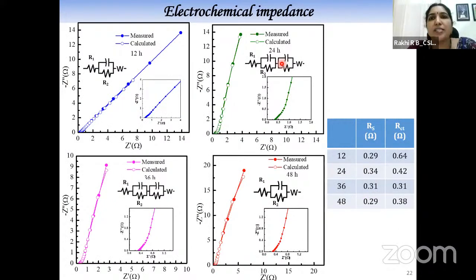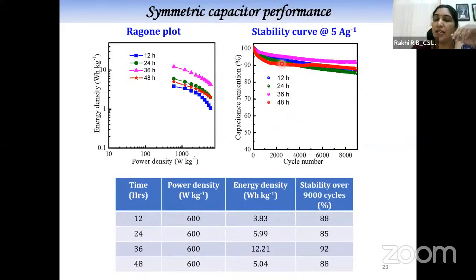Then we performed the impedance measurements. I'm not going into the details of these things. We found that the sample grown for 36 hours gave the lowest RCT. RS is the solution resistance value. It's a property of the electrolyte. If we are using 2 molar KOH, it should be more or less the same for everything. RCT is the charge transfer resistance. That RCT has been considerably decreased as compared to the conventional way by sonochemical synthesis as well.